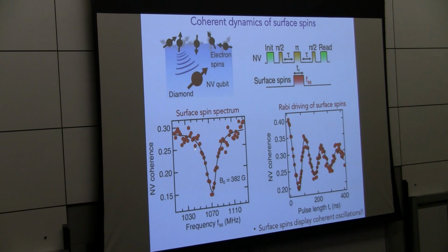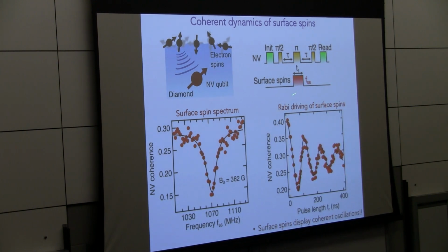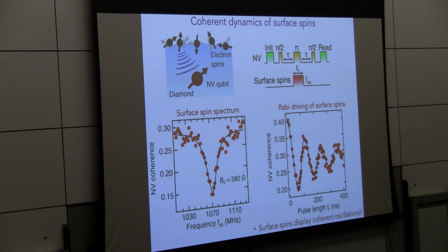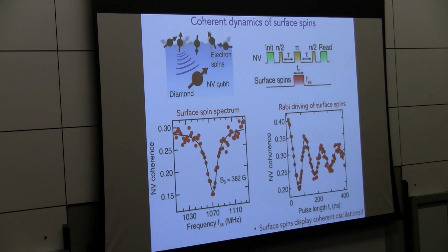What we see here is a surface spin spectrum, sweeping the frequency of a driving microwave pulse on the surface spins. We see that these are g equals 2 spins. At an applied field of 382 Gauss, we see the characteristic frequency dip that corresponds to these spin 1/2s at the surface. And they're really relatively narrow.